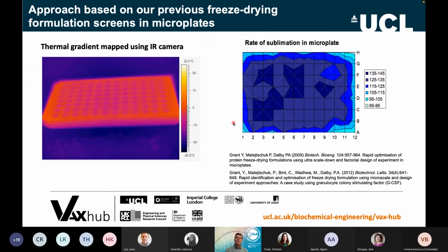So all of this is based on some much earlier work we'd done in collaboration with the National Institute of Biological Standards and Control, Paul Matashuk, where we had implemented the use of microtiter plates in freeze drying, really with a view to doing design of experiments, rather than lots of vials which use lots of material. And so what we had done in that work was to map thermally, using infrared imaging cameras, the temperature distribution across the plate, which actually was a small factor. It was fairly uniform across the plate, and we also looked at the rate of sublimation of water out of wells, and we could see that the outer wells were subliming much faster than the inner wells. And so our designs from then on were to have an outer ring of water, and then all of our formulation samples on the inside where it was reasonably uniform.